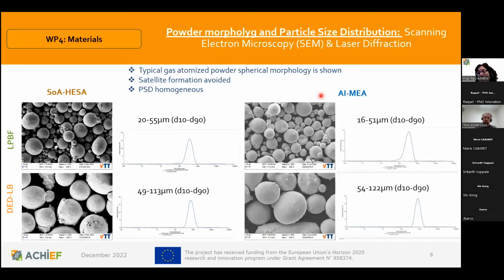If we have a look at the particles with a scanning electron microscope, we can see the size, which was also analyzed using laser diffraction. But the issue here is to check the morphology of the particles, because for us the sphericity of these particles is very important, so that the powder flows correctly through the nozzles in the case of DED, and in PBF, in order to recoat the powder properly. So the morphology is quite good for both fractions, and the PSD is also quite homogeneous, and we almost avoid the formation of satellites, which are small particles attached to the big particles.